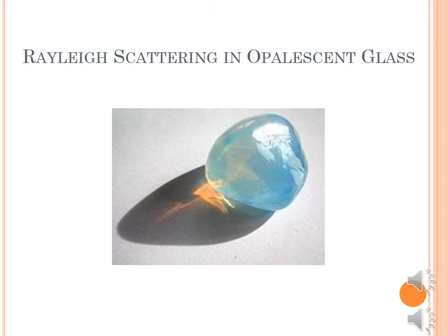In the last segment, we try to explain the coloring of opalescent glasses. Opalescence is a type of dichroism seen in highly dispersed systems with little opacity. The material appears yellowish red in transmitted light and blue in scattered light. As shown in the image, the stone appears blue from the side, but orange light shines through. The strong contrast in refractive index between pores and solid part of sintered alumina results in very strong Rayleigh scattering, with light completely changing direction every 5 micrometers on average.